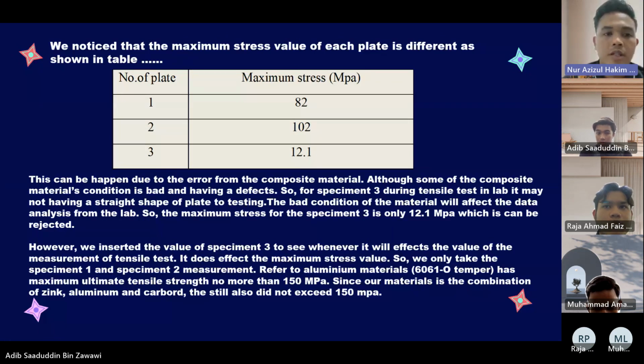Somehow, from the data we obtained from the laboratory, we noticed that the maximum stress value is different for each plate, as shown in this table. The first plate is 82 megapascal for the maximum stress. Plate number 2, 102 megapascal, and plate number 3 only 12.1 megapascal. So you can see that there is a major difference for plate number 3.